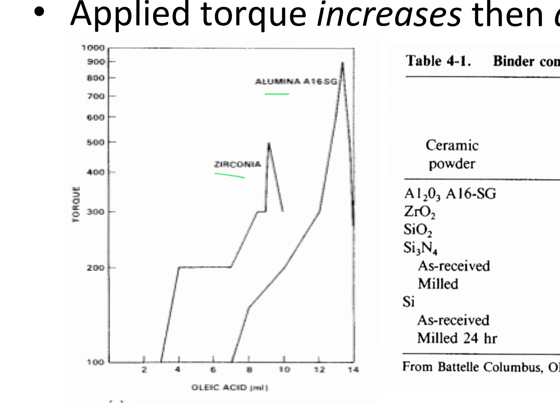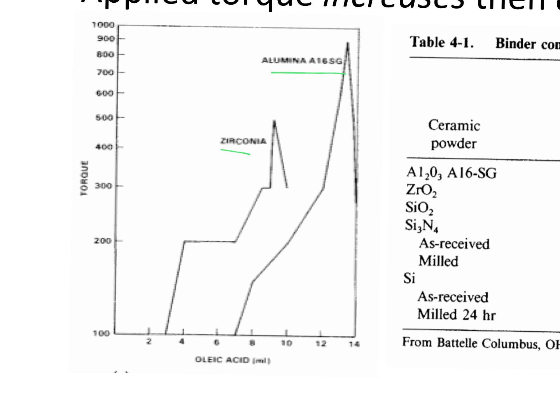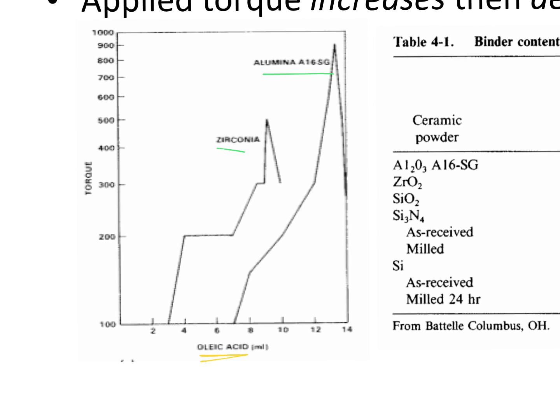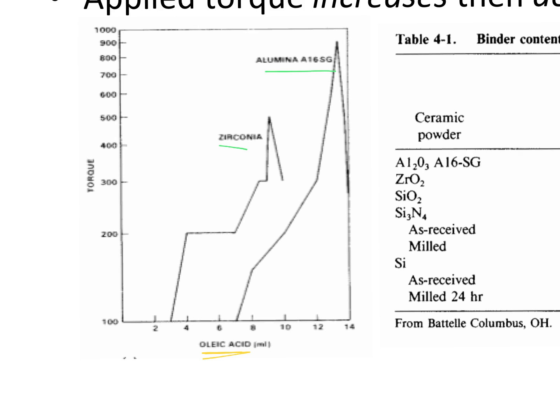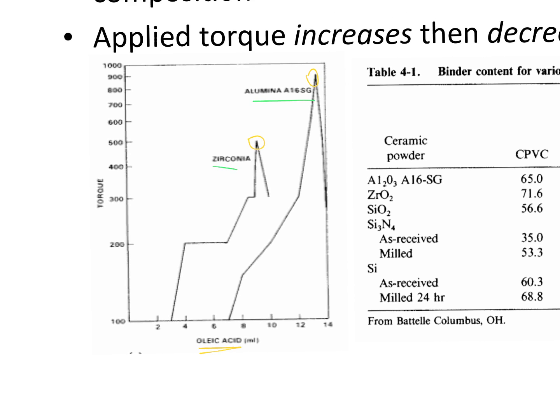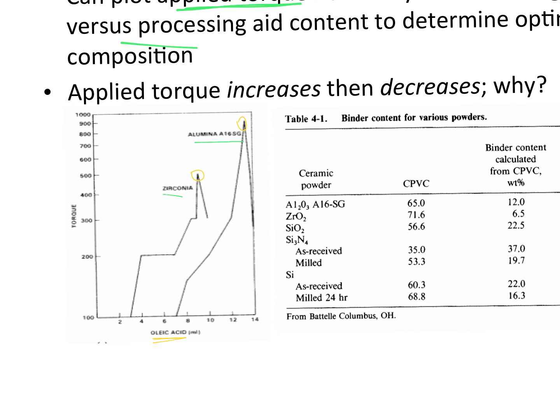A zirconia and then alumina A16 supergrind, which I mentioned before. And it also shows you this, in this case, not as a function of time, but as a function of oleic acid content, so the stuff sitting on the surface. And so what you can see is that as we increase the oleic acid content, the amount of torque gradually builds, and at some maximum value, all right, we're getting what we want. We're getting this destruction of the agglomerates and dispersion by the organic additives around it. And then after that, the amount of energy drops off.